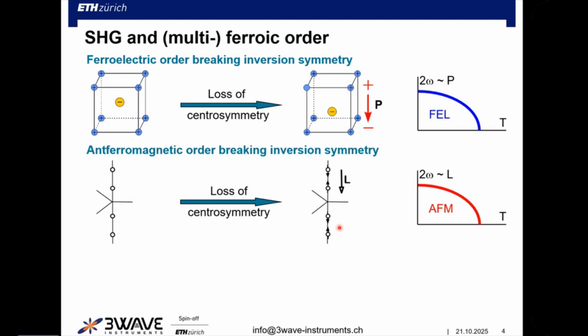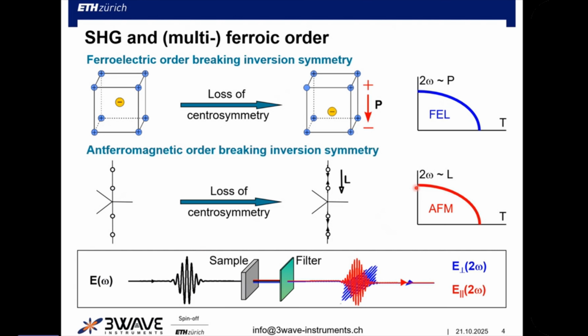Little example here. So if you take this chain of ions and you put spins on that, pointing down, up, that also breaks the inversion center of the material. So background free again, you see another second harmonic component emerging that indicates magnetic order. And you can do both in the same experiment.